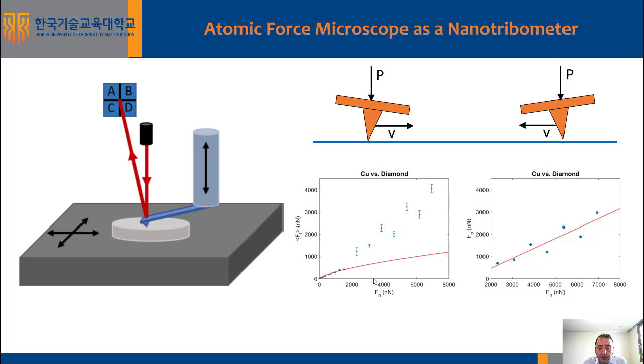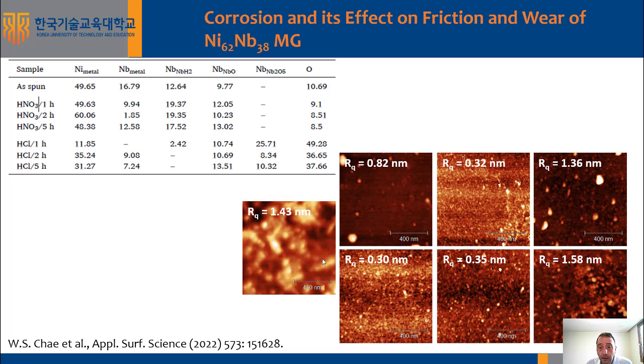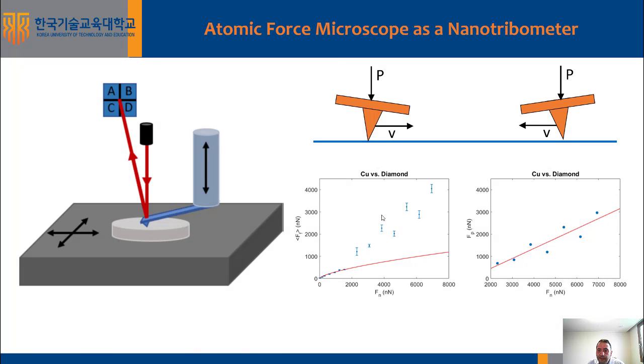Parallel to the topography measurement, we also can determine the friction force on each scan corresponding to each scan. And now, very importantly, once we have such a friction force versus normal force plot, we can distinguish between the two mechanisms, which are again shearing and ploughing. So shearing is usually fitted in the low load regime, and we usually know where to stop, because once ploughing sets in, we first have a significant increase in the error bars in our friction signal, and also we observe a roughening of the surface.